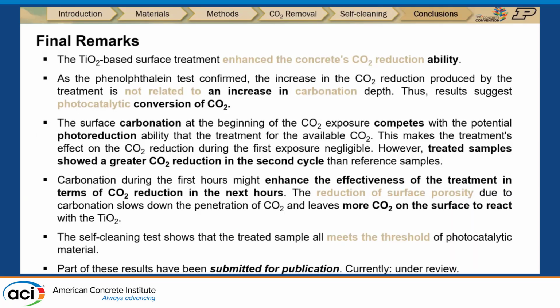So these are some final remarks. We did see that the titanium dioxide-based surface treatment enhanced the concrete's carbon dioxide reduction ability, and the phenolphthalein test told us that it is not related to an increase in carbonation. It suggests a photocatalytic conversion of the carbon dioxide. In the first cycle, we saw that the carbonation competes with the photoreduction, but in the second cycle, the treated samples showed a greater carbon dioxide reduction than the reference samples. So the carbonation in the first few hours might enhance the effectiveness of our carbon dioxide reduction.